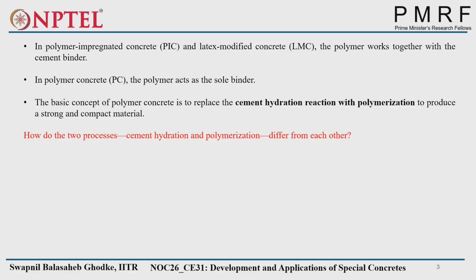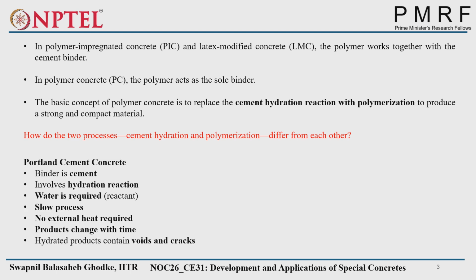So how do the processes of cement hydration and polymerization differ? Basically, in Portland cement concrete the binder is cement. It involves a hydration reaction and water is required for that purpose. It is a slow process. We have the initial setting time and final setting time. No external heat is required in this case because the reaction itself emits heat. That is an exothermic reaction. Products change with time. Means in the initial period we will have a different value of stiffness or modulus of elasticity, and after some time we will have a different modulus of elasticity. So stiffness changes with respect to time. The hydration products change with respect to time. Hydrated products contain voids or cracks also.